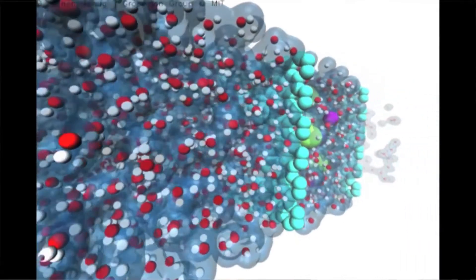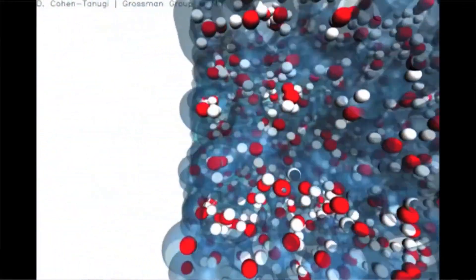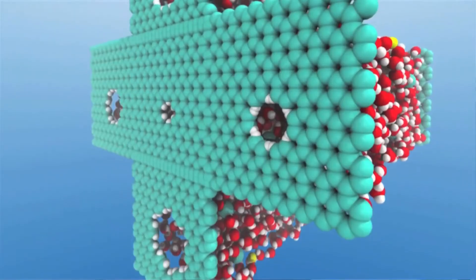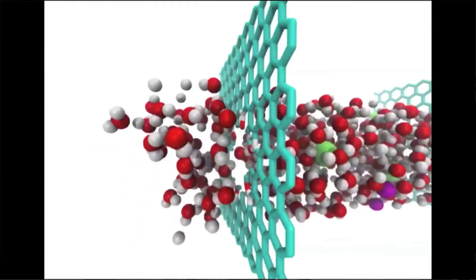And that harnesses the fact that graphene is very impermeable. Even very light gases don't pass through. And that means that if we were able to tailor the size of the pores within the graphene lattice, it might be possible to produce a very selective filter or perhaps use smaller graphene sheets and use the pathways in between the sheets in order to tailor the porosity or the permeability of the membrane.